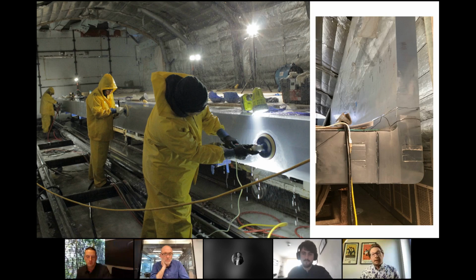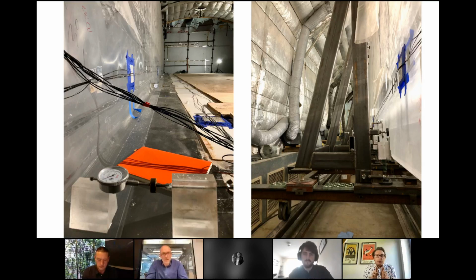Bonding two materials together, particularly acrylic with a resin, is not a simple process, largely because we're talking about very heavy panels. The wall panels are about 12, 13 tons. When the syrup is poured into that gap, it goes through an exothermic reaction: it gives off heat and expands. As it starts to cure, it shrinks again, past the original nominal joint width. If the two panels were kept rigidly in place, you'd generate tension loads in that syrup, and you'd form cavitation and bubbles. Bubbles, along with being aesthetically undesired, can cause stress concentrations in the material too.